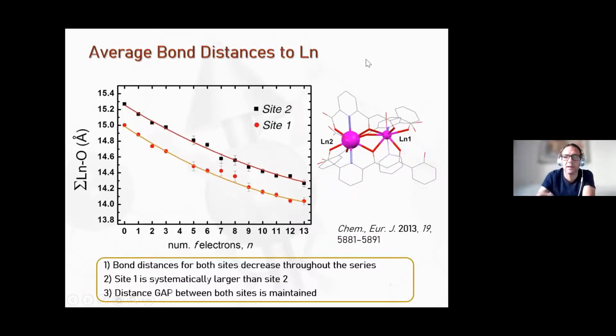We've realized a few interesting features on this series of compounds. For example, if we compare the bond distances for the entire series of complexes, the trends of lanthanide contraction are fulfilled. But one interesting thing is that we see a systematic difference on average bond distances from one site to the other site.